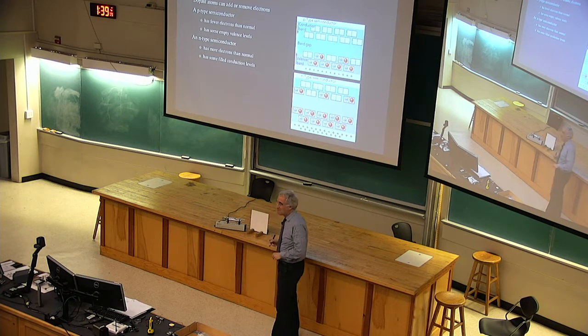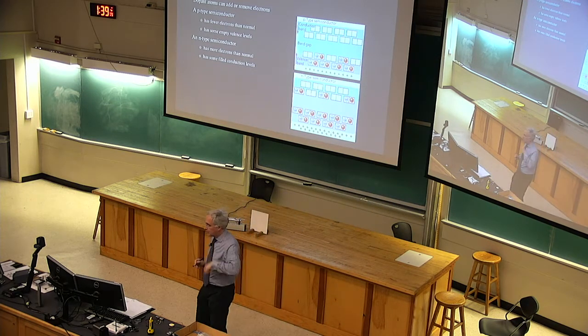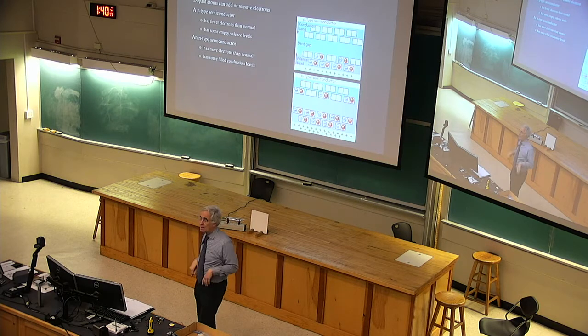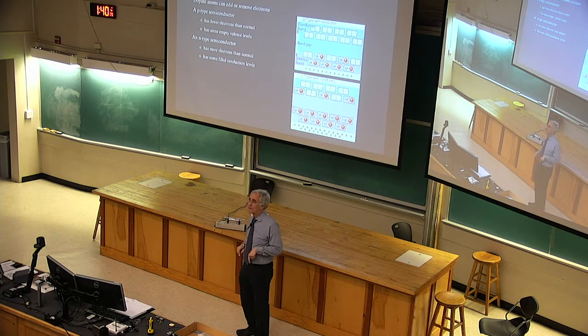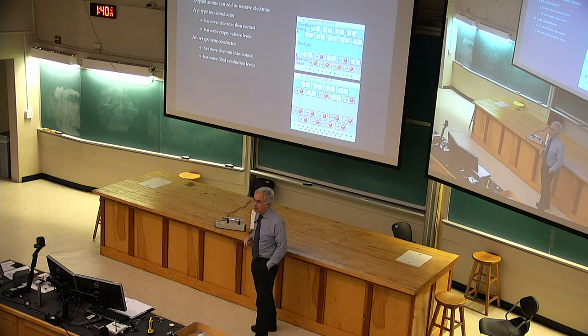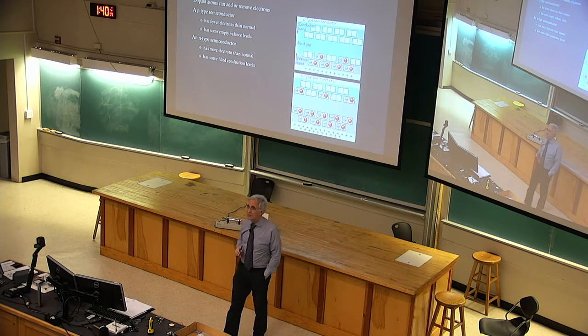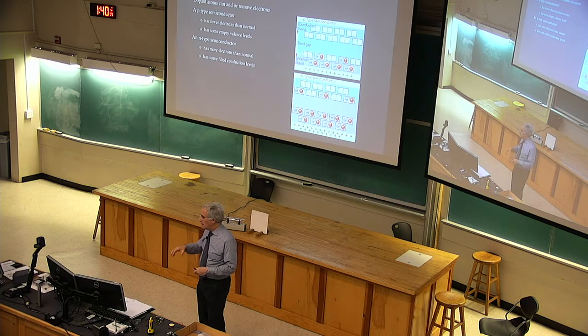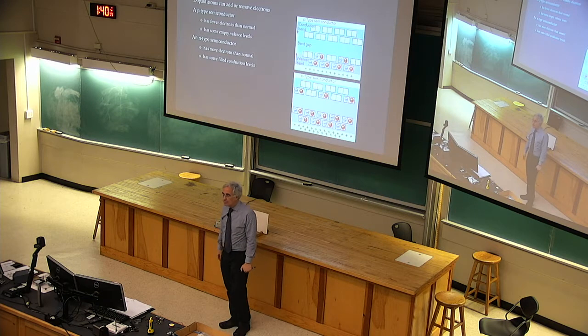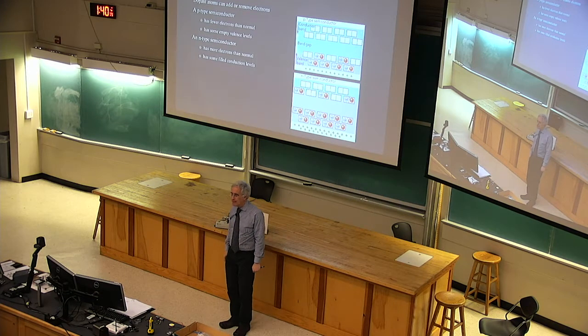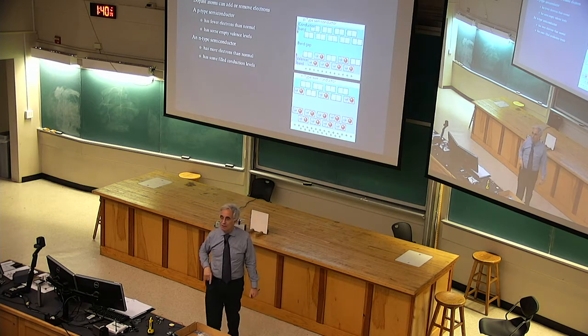All right. What if you start mucking around with the silicon? So I do have silicon in mind when I'm talking about this, but there are other semiconductors, some of which are important and in common use. But we can stick with silicon, it's good enough. If you take silicon and you remove a couple of atoms from the overall solid, and you replace them with atoms that have fewer electrons. For example, to the left of silicon in the periodic chart is aluminum. The aluminum atom is very similar to silicon, except it has one fewer proton in its nucleus, and therefore it attracts one fewer electron.